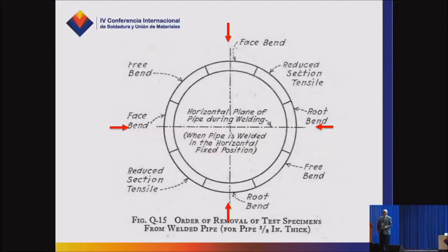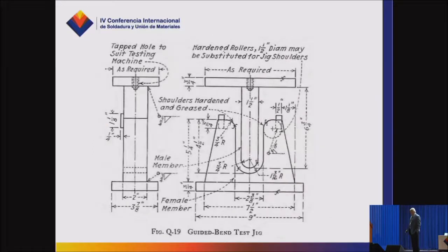The ISO 9606 standard had inadvertently been changed to have its test specimens removed, as you see in this example on the screen. Was not intended, I don't think, but we ultimately discussed where bend test specimens should be removed. And the argument was made that probably the most difficult position for a welder to make a weld on a piece of pipe is coming down from underneath, up and around, on the inside, on one side of the weld. That 45-degree mark was really a challenge for the welder to make a sound weld. So the ISO committee agreed to put the bend test specimens in the same location that ASME has. So that was a good thing.